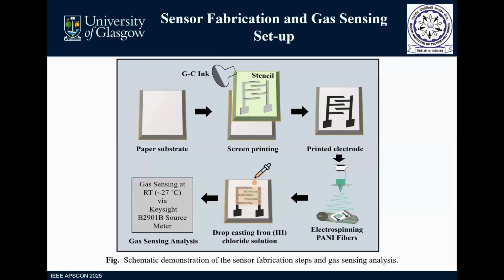We have used a paper substrate on which we printed an electrode using carbon graphene with the screen printing method. After printing the electrode, we annealed it at 60 degrees Celsius overnight. Then we electrospun the PANI onto that substrate. After electrospinning the PANI, we drop casted iron chloride solution and annealed it to develop Fe2O3 nanoparticles. Our sensor was then ready, and we characterized it for gas sensing in a controlled environmental chamber using a Keysight source meter.